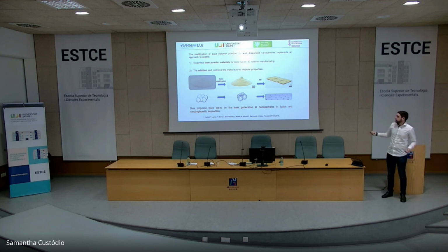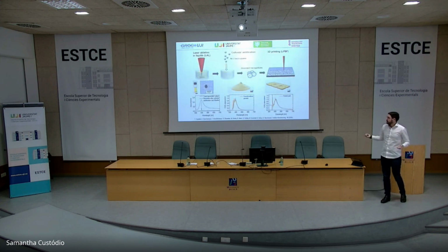What we do afterwards is just the regular printing of these materials. So we use this laser powder bed fusion that is fusing the material, and then we can print some samples that still keep the nanoparticles on the surface. Here you see an example.